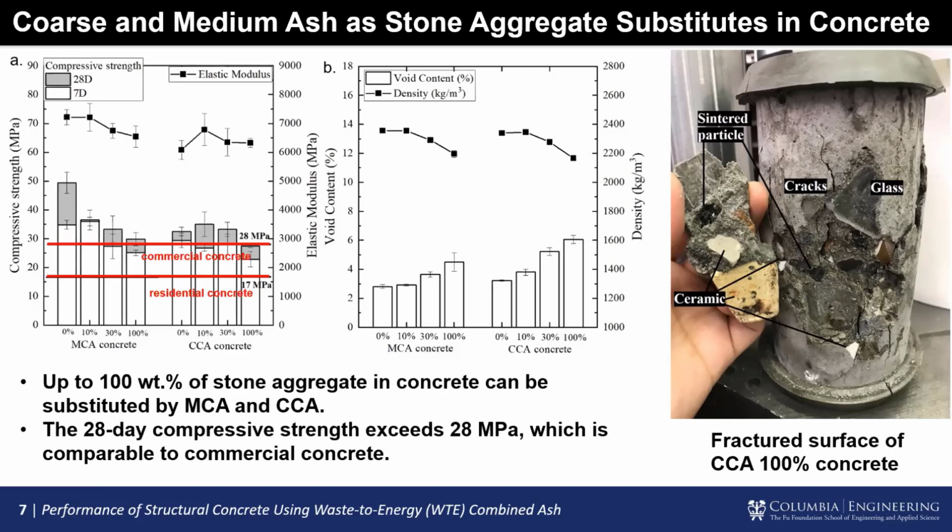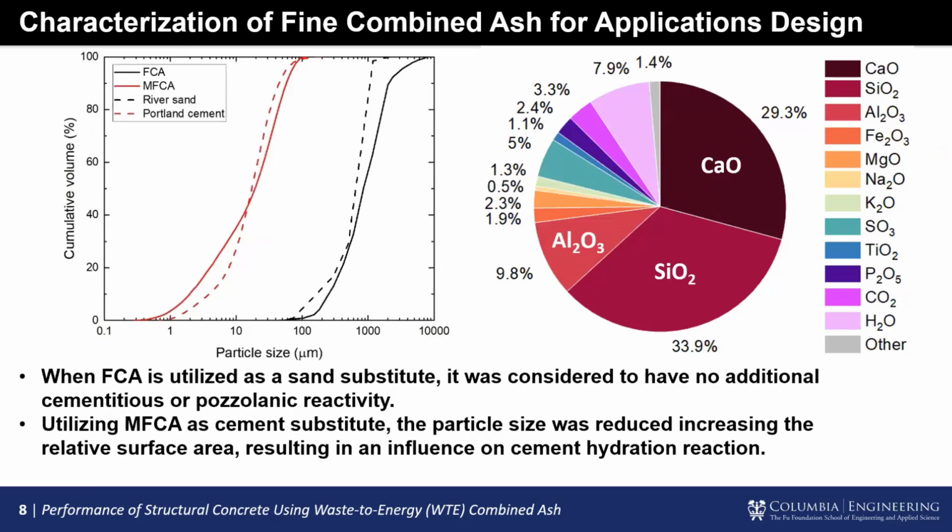As we can see from this photo, for the 100% ash concrete, the fracture surface, the small pieces of ceramic and glass result in cracks during the compression test. So this is the result for these two ash fractions: mechanical strength decreases. And this is the characterization for the fine combined ash